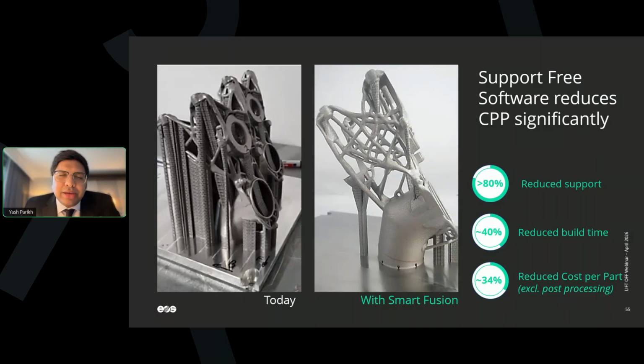So what it does is it allows us to control the thermal balance of our parts. This is an example before I go to the real work that we did with this, but this just tells you that because of controlling thermal history in a way, you don't need that much support structure. Support structures are more than just thermal history, but in essence it is basically connecting your heat sink, which is the build plate, to that part, so that you can avoid any part lift off and things like that. But this is the core message that I'm trying to give you. So go to the next one.